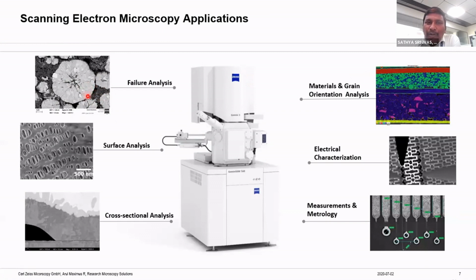So in that particular surface information, this is one of the typical samples, which is a battery separator, which is completely an insulator. So you cannot use higher kVs for such types of samples, but still you can do the analysis using this electron microscopy at very low kVs.